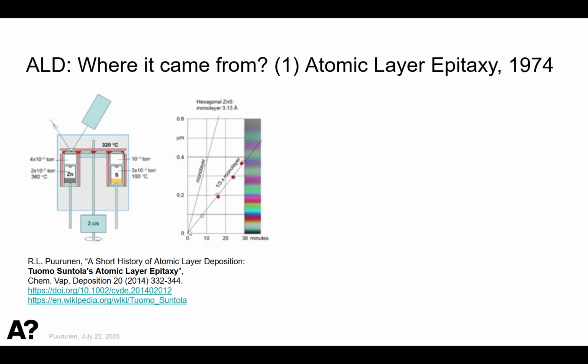And it took some time before anything started happening, because they were expecting a monolayer of zinc sulfide per reaction cycle, but that didn't happen. The growth was slower, but things started then happening, and they happened linearly. So the purple color was coming back, and this was repeatable. According to what Suntola has told me, they were first disappointed because they were expecting this full monolayer growth, and that didn't occur.